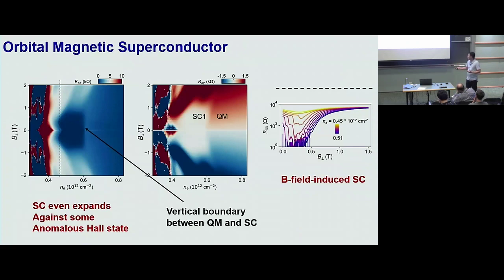And we think this tells us that the superconductor itself is an orbital magnet. And that is why it is fluctuating. Because orbital magnet can fluctuate from K valley to K prime valley, or magnetization pointing upward to downward. And orbital magnet can be stabilized by an outer plane magnetic field. Okay, that's why you got hysteresis. So time reversal symmetry is broken at the orbital level in the state.